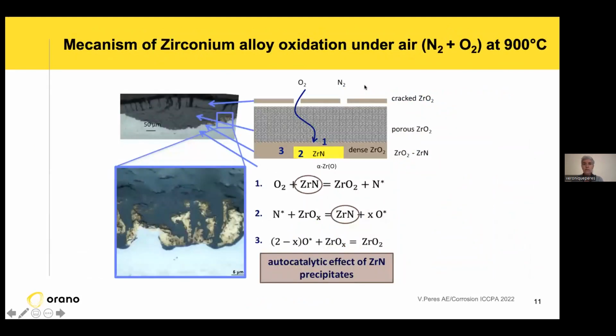Why? Because we have these mechanisms. I will not explain this mechanism in detail, but you can see in gold the precipitates of zirconium nitride. They are here at the metal-oxide interface. And this nitride is very unstable, and with oxygen coming from the external part of the tube, due to the porosity, it can release oxygen to make the corrosion of the metal. And there is an autocatalytic effect of the nitride precipitate.